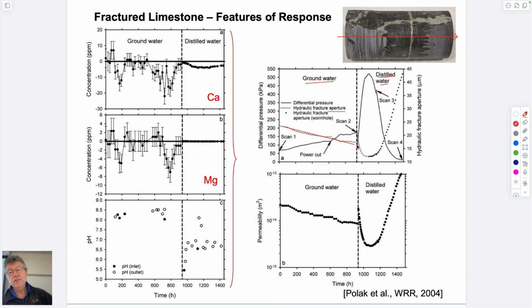But when you start injecting distilled water, all of a sudden you increase the rate at which you dissolve material, presumably by pressure solution, but then all of a sudden spontaneously the permeability starts going up again. And so we explained this as the idea that you have a fracture that has these capillary flow tubes with fluid flowing into the page. As you net dissolve it, the walls of the fracture grow together and the permeability decreases.